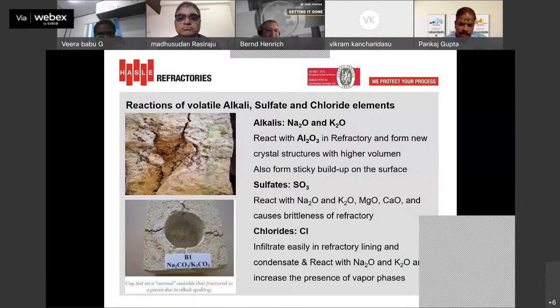So how do these volatile gases and acids affect the refractory performance? Basically, these castable refractories are based on alumina, and alkalis react with the alumina present in the refractory and form new crystal structures with high volume. There is expansion of these phases, and because of that the refractory cracks. That is also called alkali spalling. Here you can see this cup is made of castable and heated with alkalis, and alkali spalling can be seen, and it is fractured into four parts.